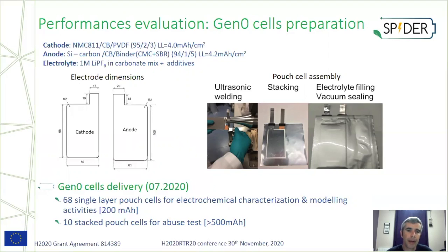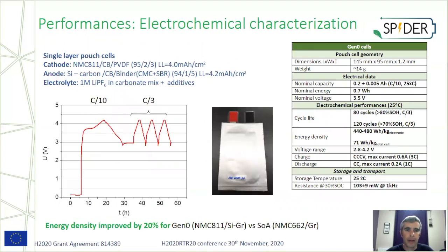We prepared 68 single-layer pouch cells for electrochemical characterization and modeling activities. The pouch cells were distributed to partners for tests, and 10 additional stacked pouch cells with a higher capacity for abuse test. You can see on the graph the first formation cycles with a low rate cycle at C/10 and 3 characterization cycles at C/3. All the characterizations of the cells are detailed in the table here.